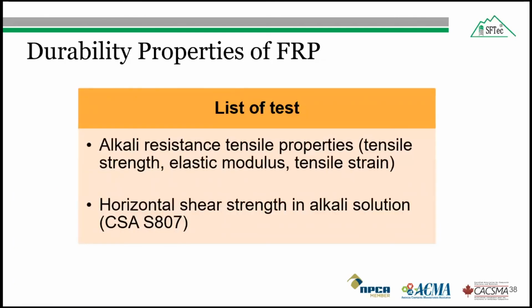Now, coming to the durability properties of the FRP bar. The tests we do for the durability properties are the same as in the mechanical properties. Just here we do them for the alkali resistance. Alkali resistance means we do the tensile properties, including tensile strength and elastic modulus, but we keep the samples in the alkali solution for 3 months. After that, we do the test.